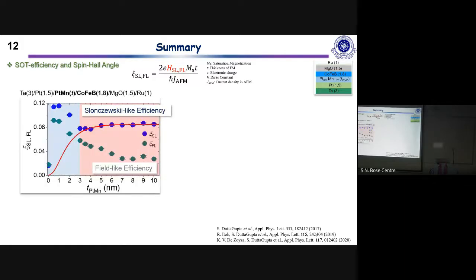So finally, after getting these effective fields from the currents, we can define this parameter xi, which is the efficiency of the charge to spin conversion, and then we can plot it as a function of the thickness of the antiferromagnet. What we see, first of all, is very interestingly that definitely the antiferromagnet is a source of spin Hall effect. And concurrently, several people other than us also quantified it using other techniques.